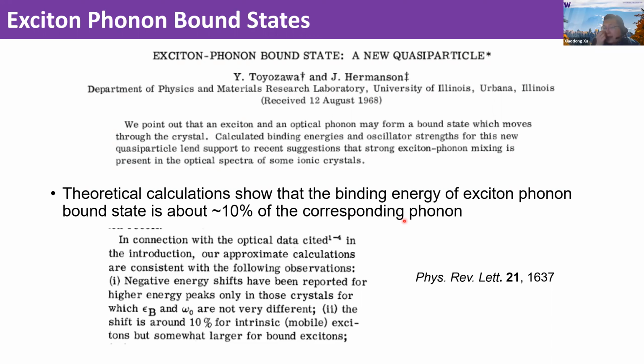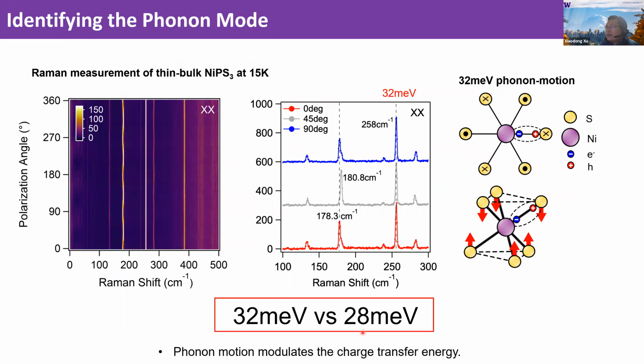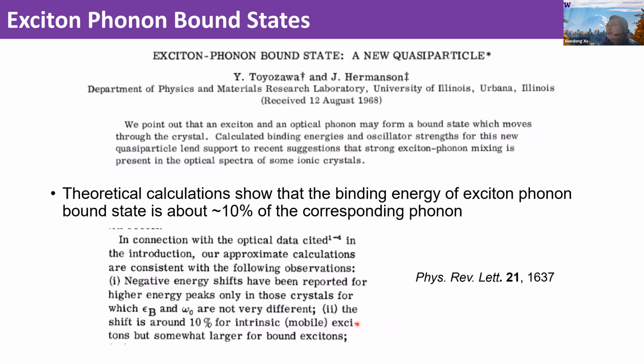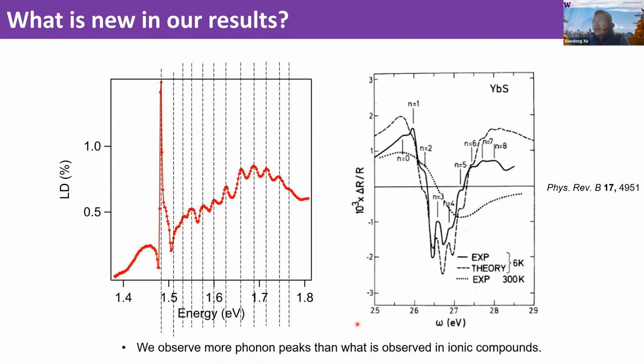So what it means is, if you have these exciton phonon bound states and you measure the period in the spectra, you'll find the period should be about 10% less than the corresponding phonon energies. So that's exactly what we have. What we measure here is 28 meV and the phonon is 32, so it's about 10% less. So the binding energy is basically 10% of the 32. Okay, so now we can attribute these wiggles to this exciton phonon bound state.